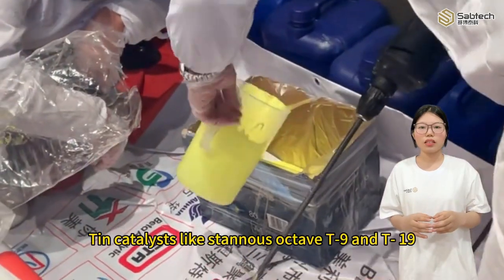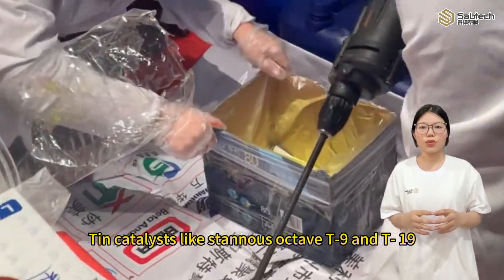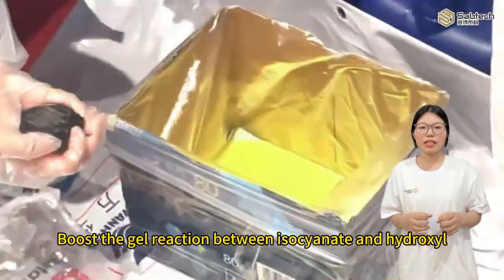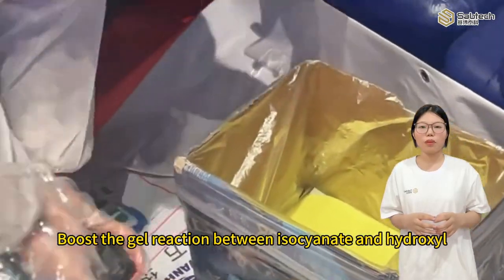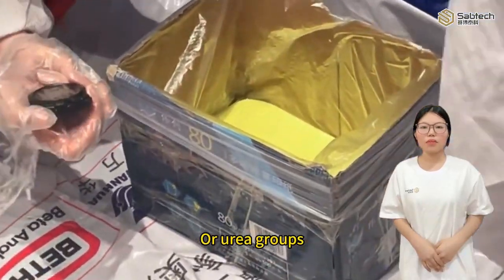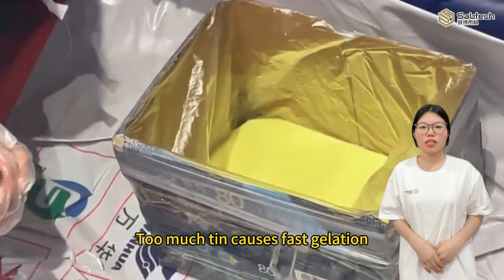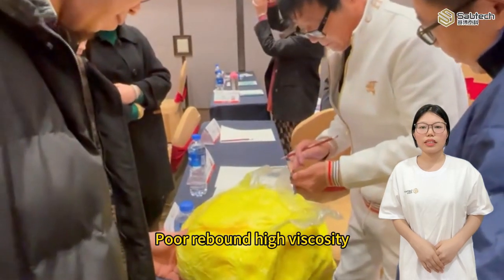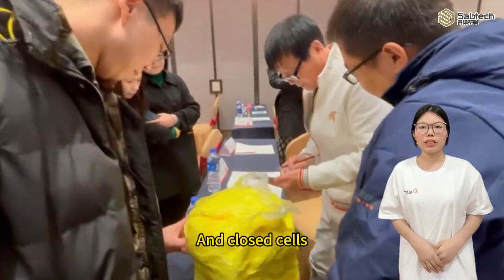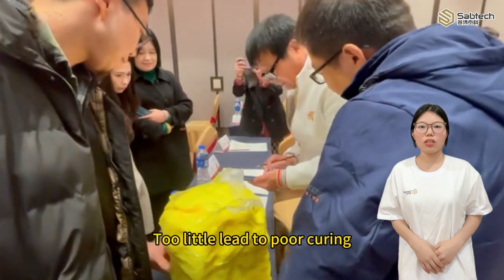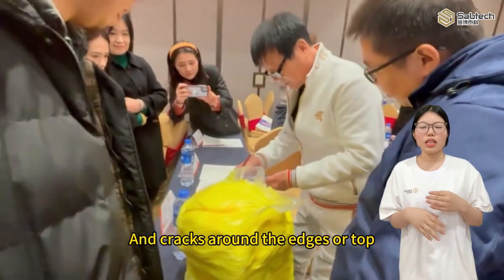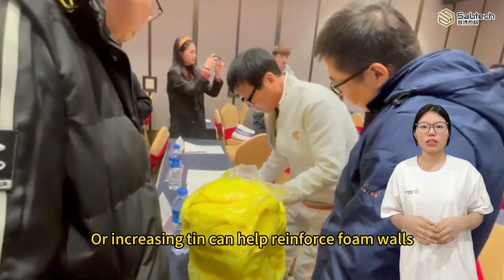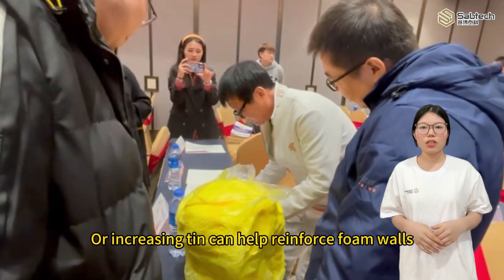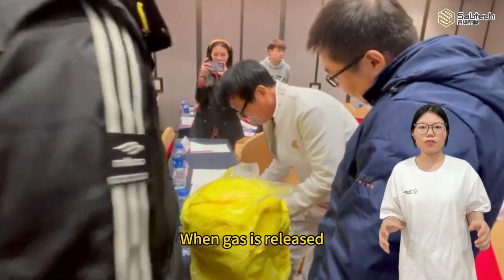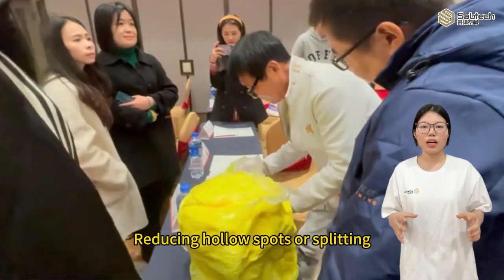Tin catalysts like stannous octoate, T-9 and T-19 boost the gel reaction between isocyanate and hydroxyl or urea groups. Too much tin causes fast gelation, poor rebound, high viscosity, and closed cells. Too little leads to poor curing and cracks around the edges or top. Reducing amine or increasing tin can help reinforce foam walls when gas is released, reducing hollow spots or splitting.